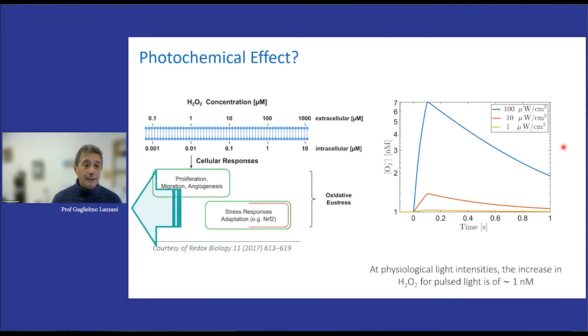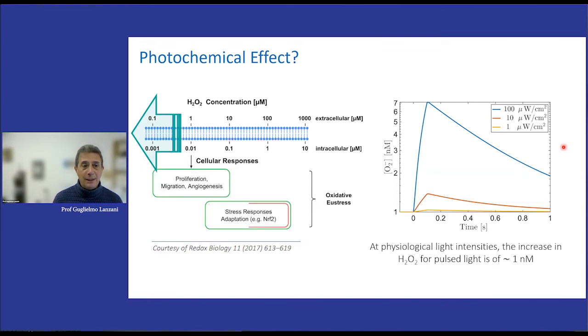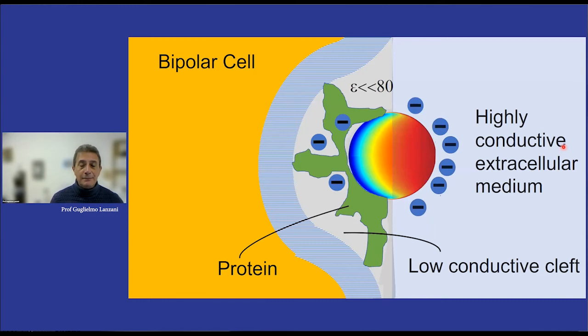But now, according to our investigation, the minimum concentration that gives an effect is in the micromolar region, while we are unable to go beyond the nanomolar concentration, even for the very high light intensity, which becomes too high for the retina. So we think we can exclude the role of superoxide and hydrogen peroxide as a sensitive medium.